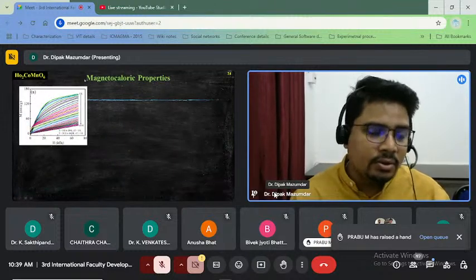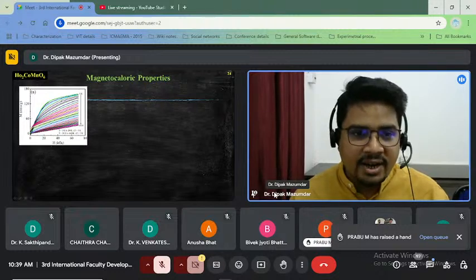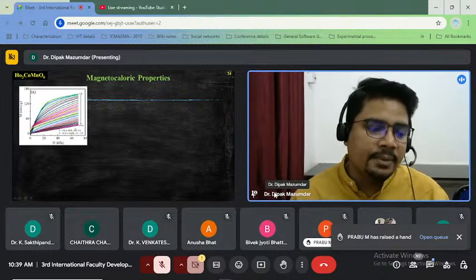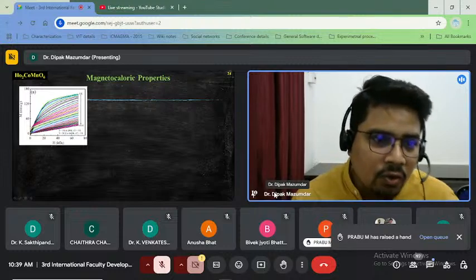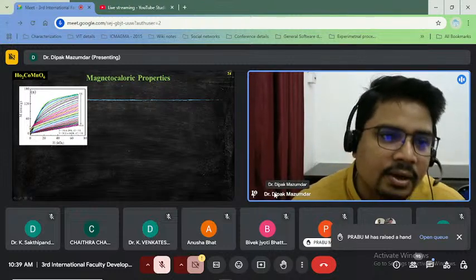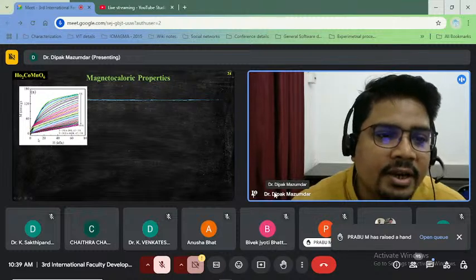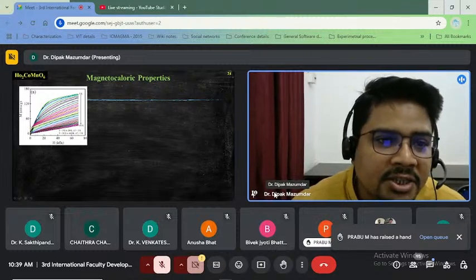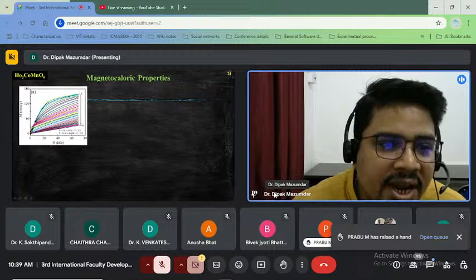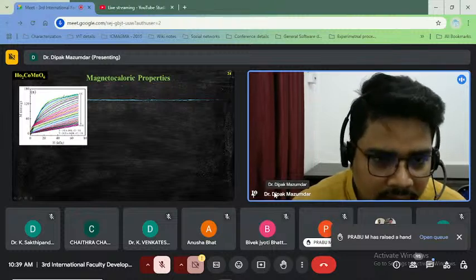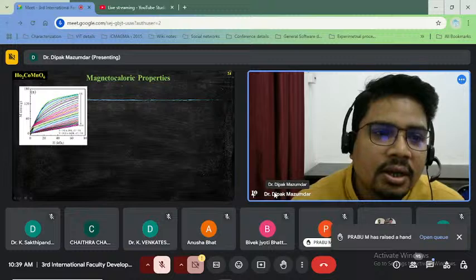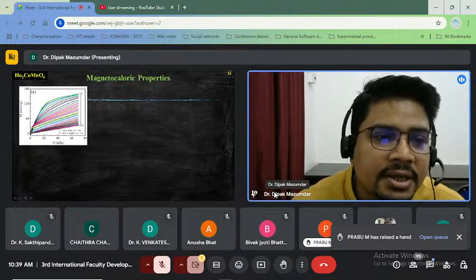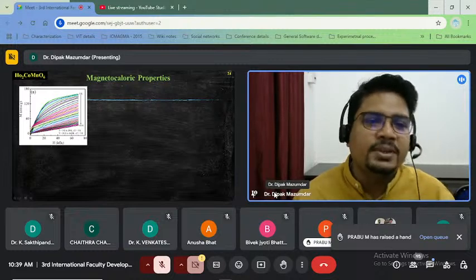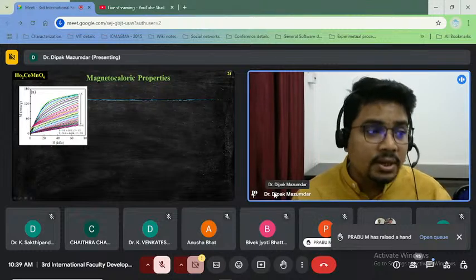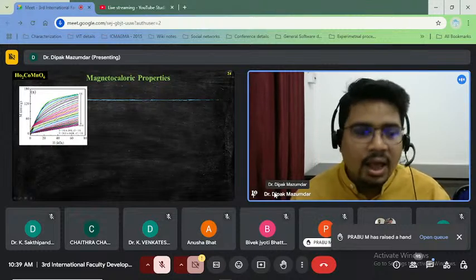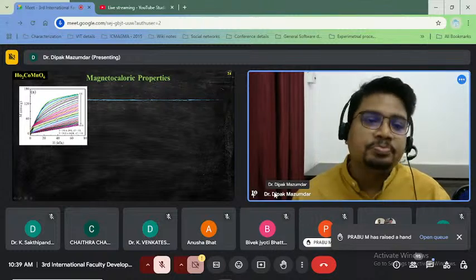So to study the magnetocaloric effect, I have taken several magnetic isotherms at different temperatures, and in the low field region you can see a crossover of magnetization data. For low temperature, the magnetization increases very sharply. But as soon as you increase the temperature, the magnetization increases very slowly, or you can say the slope is very low. So this is very good for getting a high value of magnetic entropy change.